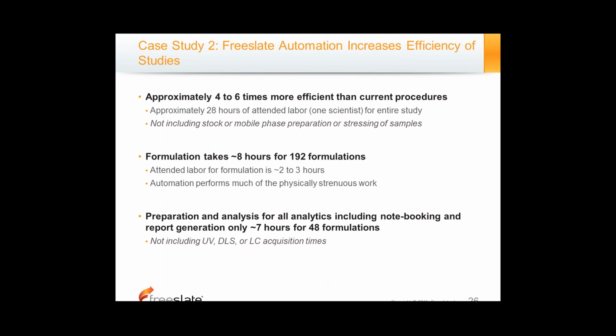And what's important to note there is that for this entire study, for all 4 stress points, or for T0 and the 3 stress conditions, it took about 28 hours of attended labor for one scientist to do this entire study. What's also important to note here is when we use the system to make the formulations, we're able to make about 200 vials filled with unique formulations in about 8 hours. And the idea here is that we have only about 2 hours of that is attended labor, and the automation is performing much of this physically strenuous work.